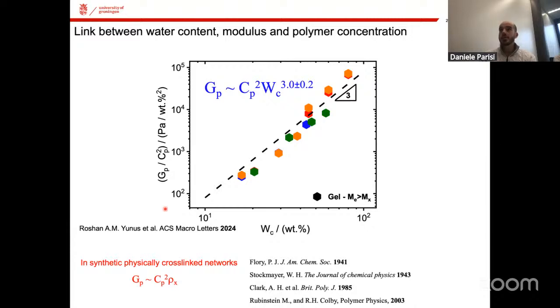Only the water content is very different from what we know in terms of cross-link density. We say that water acts as a cross-linker, but of course it's much more than that. It's a much different physics, I would say. Okay, so this is a universal equation? Yeah, this is a valid equation. It's just that the power law for the water content seems to be strongly dependent on the rigidity of the polymer chain. But it's quite an interesting tool, because you change the water content a little bit, but with a log scale here, you can change the modulus almost at will. So it's very sensitive to water. Okay, thank you, Daniel.